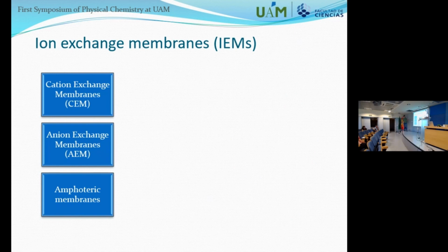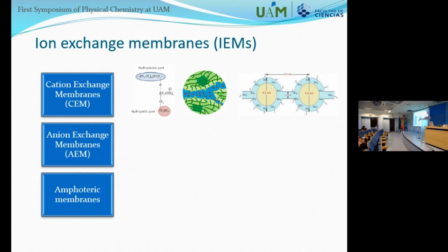So just to have an overview of what types of ion exchange membranes do we have? We have the cation exchange membranes. So what we have in this case is that, well, it's very small, but you can trust me, we have negative fixed charges in the membrane structure. So these negative fixed charges help for the conduction of positive charges because they are attracted, and it helps to conduct the positive ions through the membrane. The most known and typical cation exchange membrane is the Nafion membrane, whose structure is here. It has a hydrophobic part and a hydrophilic part with the sulfonic acid groups, and it forms this kind of channels. So they have been tested for so long, they are very good, but they are very expensive also.